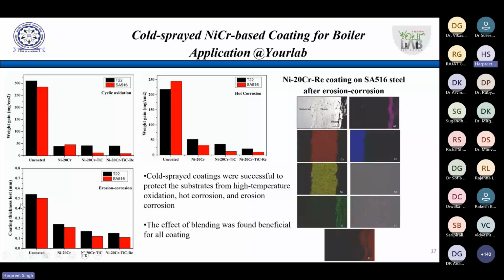So what we have done, we have calculated that thickness loss after 1500 hours, and here you see the results. You see this uncoated sample was also hung, and then the coated samples were also hung in this manner. You can see the clear cut effect of these coatings, right? So this is one study which we conducted, and you can see the success of these coatings from these micrographs, that nothing has happened. Not even any significant oxide has formed inside the coating.